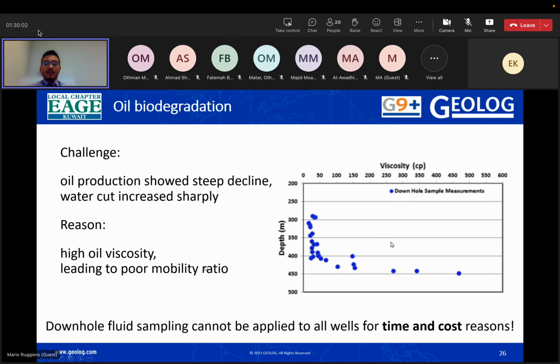We can use the biodegradation markers, for example, in this case. Our challenge here is that the oil production showed a steep decline when the water cut increased, so close to the oil-water contact, the oil was getting more viscous. The problem is high oil viscosity and poor mobility ratio, and downhole sampling couldn't be done in all wells and at many different points because of time and cost reasons.